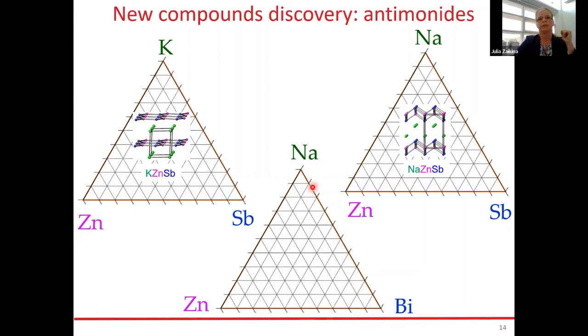And before we started research in these three systems, there were only two compounds pictured here in those two systems, and they have composition 1-1-1. The structures of those compounds are quite different, even though the composition is the same, noticeably because of the difference in the ionic radii between sodium and potassium. Nevertheless, there were only two compounds in the systems containing antimony, and none of the ternary compounds in the system with bismuth. So those systems are very underexplored, as you can see.